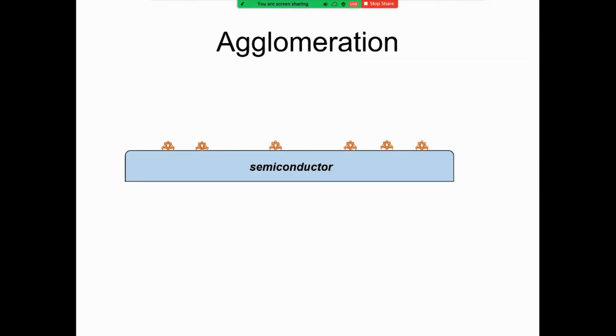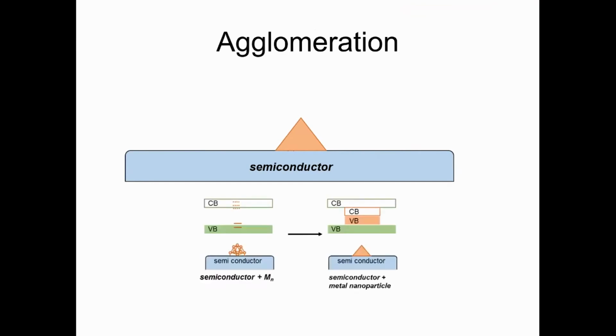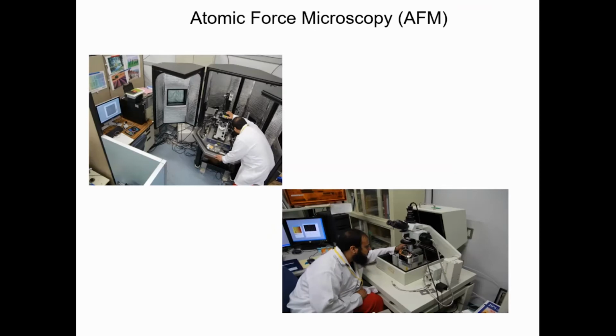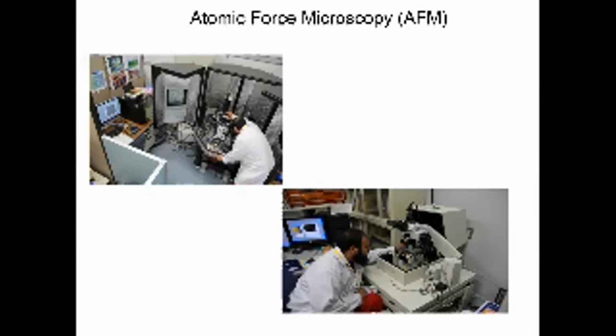We usually try to avoid the aggregation as much as we can, because this is not our target, and this is a huge challenge in nanoparticles, even at the nanoscale, because you will end up with a different electronic structure. And there is no benefit of being precise on the gold nanocluster itself. We need to target a specific size regime to have it do a specific catalytic reaction. And to measure this agglomeration, we need scanning probe microscopes, like atomic force microscopy and STM, the scanning tunneling microscope, to measure the degree of the aggregation when we deposit them on the metal oxide itself.